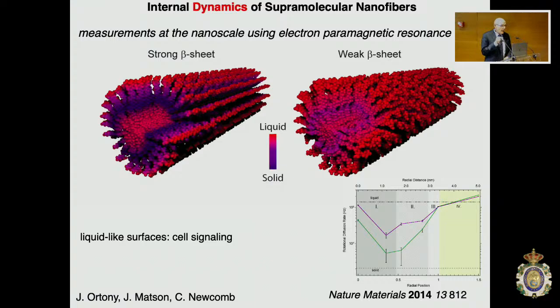And if you keep going another few nanometers to the very center, it's kind of a pinkish color, not quite as red as the surface, because in the middle it is more like a liquid crystal. So you have 3 forms of condensed matter in the space of about 7-8 nanometers. It's really fascinating to see those changes that way. And so this is one of the first things we saw in the dynamic department in 2014.